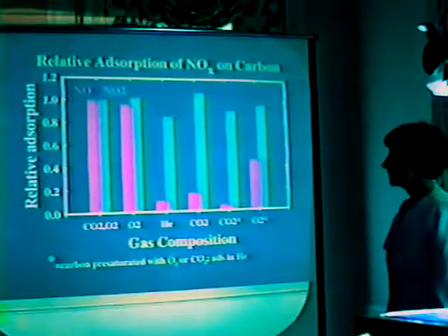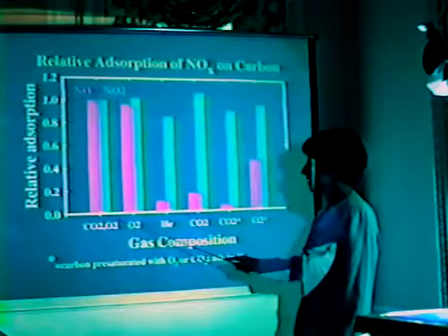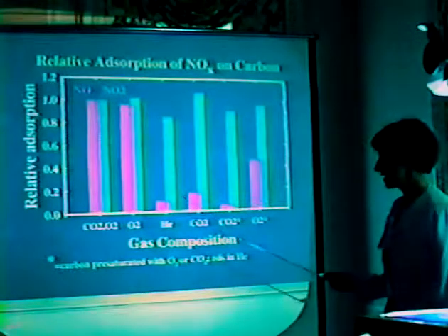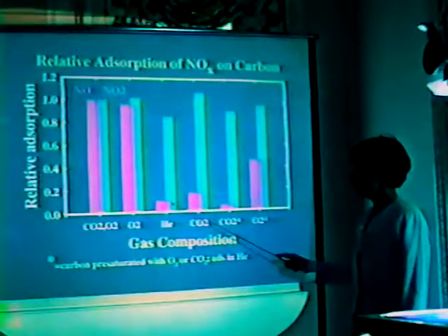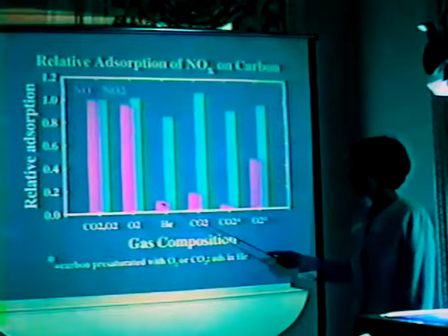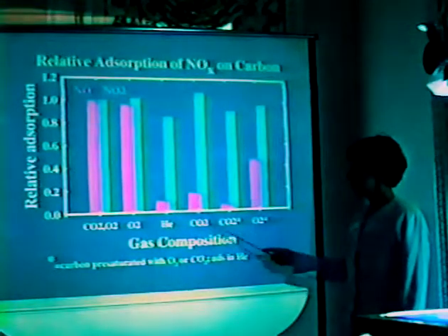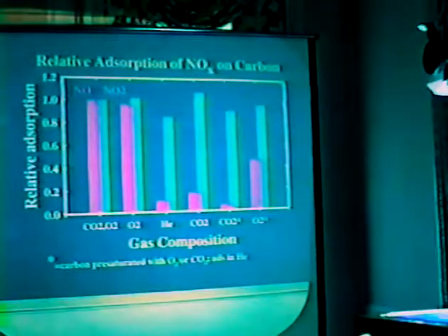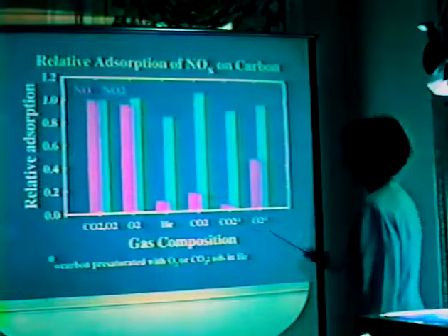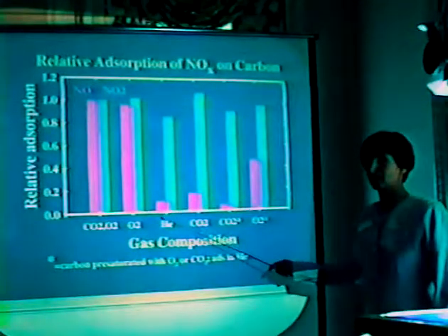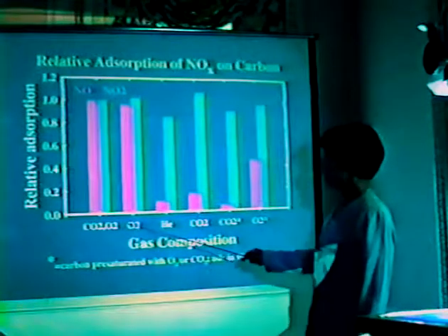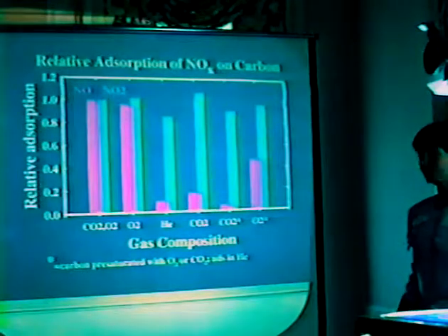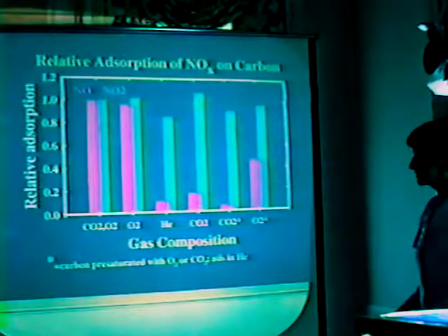And what's immediately obvious here is that for NO, oxygen is required, and CO2 does not appear to be detrimental to the reaction. If you look here at the very little adsorption that you see with NO and helium, this is really what the information that we found in the literature before we started this study. Very low levels of adsorption of NO, and the significance of this work is the fact that when you have oxygen present, you get a significant increase in the level of NO adsorption onto activated carbons.